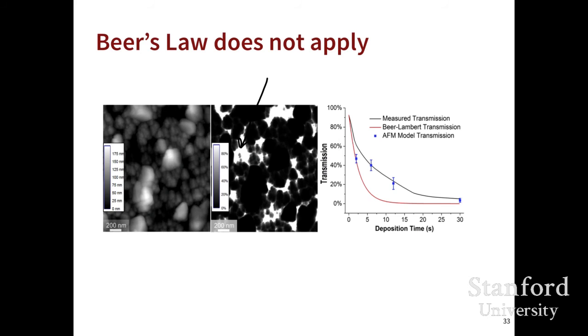Probably the good side of it is that our transmission versus deposition curve isn't quite as steep as the Beer's law curve. And that means that we can have just slight variations in film thickness and not have a huge variation in transmission. But I will say we're going to at least try not to have the metal plate everywhere, because if it does, and we get to the Beer's law curve, then we will get low transmissions with less metal, and that will mean with less current, and that'll mean that we can switch the window faster.